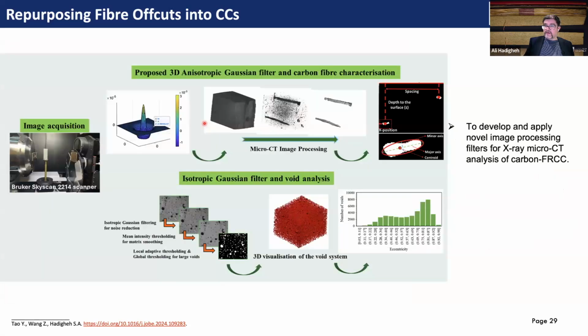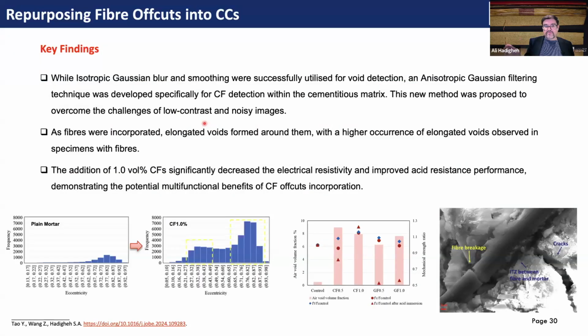And that's why we looked at how we can characterize that, because we used micro-CT to analyze voids and also carbon fiber inside the cementitious material. And interestingly, we realized that by addition of that carbon fiber, you see some specific shape of void forms inside the cementitious material, and those elongated voids lead to higher permeability and lower mechanical properties. So it is quite interesting to see that kind of performance, the shape of void and the relationship between the shape and also carbon fiber and dosages of carbon fiber inside the cementitious material.